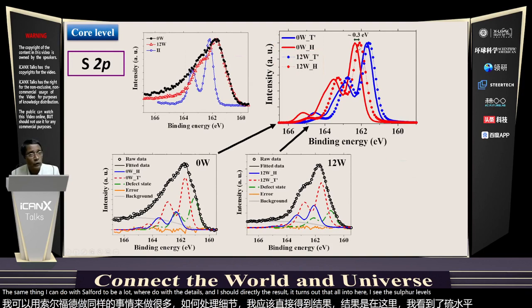The same thing I can do with sulfur 2p. I'll not bore you with the detail, and I'll show you directly the result. It turns out that here also, the sulfur H phase signal and the T phase signal, both for the unwashed sample, are at higher binding energy by 0.3 electron volt, whereas the thoroughly washed one is 0.3 electron volt lower in binding energy.